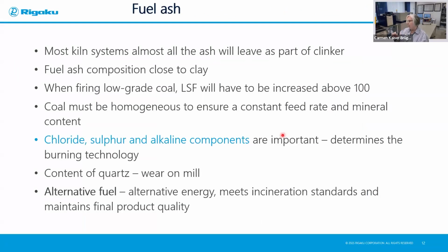If we look at the fuel ash, you can see that in most kiln systems almost all the ash will leave as part of the clinker. And the ash composition is very close to the clay because it has a high amount of silica and alumina and calcium. So when firing low-grade coal, the LSF will have to be increased above 100. And the coal that we use normally needs to be homogeneous to ensure a constant feed rate and a mineral content that we can predict. Elements like chlorine, sulfur, and alkali components, like sodium and potassium, are very important, and they will determine the burning technology. The content of the quartz will cause wear and tear in the milling process at the end. So when we have the clinker and we need to mill it, it will have an effect.